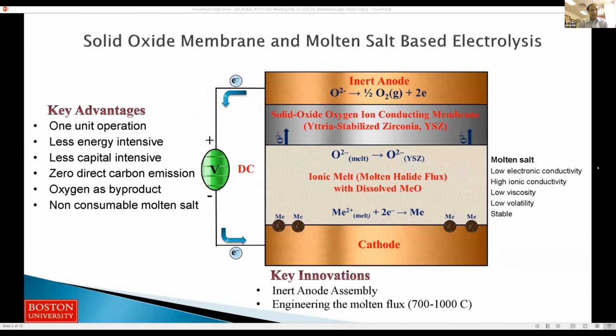Here is a schematic of the electrolytic device. The heart of the device is the oxygen ion conducting solid oxide membrane. One side of the membrane, you can see at the top, is the oxygen producing anode, and the other side of the membrane is exposed to molten halide flux or salt containing the metal oxide. The cathode is placed inside the molten halide salt, and then an electric potential is applied between the anode and the cathode. And when this potential exceeds the dissociation potential of the metal oxide in the halide salt, the metal is reduced at the cathode, and the oxygen ions in the salt migrate through the oxygen ion conducting membrane to the anode, where they're oxidized to oxygen gas.